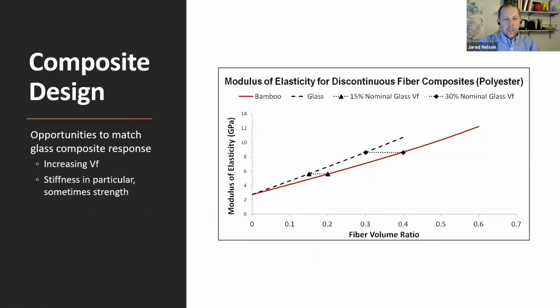Now, if we then go ahead and say, okay, if we're looking at an opportunity that utilizes 15% glass as a volume fraction, so 15% of this chunk of material is fiberglass. Well, one of the ways that we can actually see a benefit and bamboo can be competitive is if we increase that fiber volume fraction to 30% for the bamboo. And so in that case, we can see that if we compare the 15% case, our modulus of elasticity, in order for that to be the same, we have to bump up to just over a 20% volume fraction from fiberglass. Sorry, let me slow down for a second.